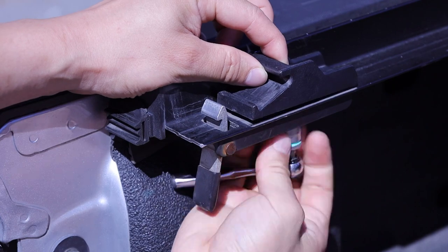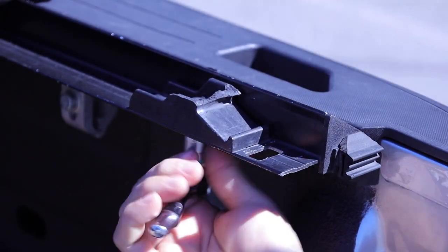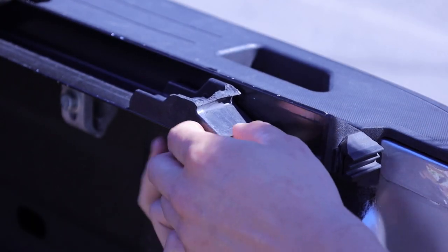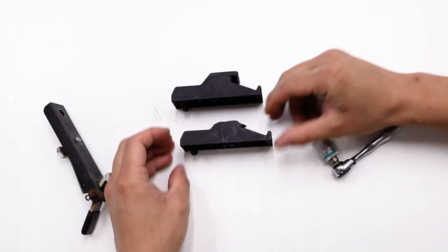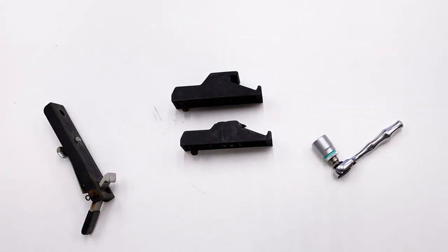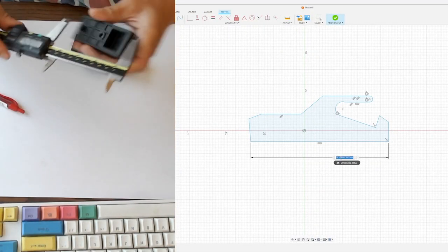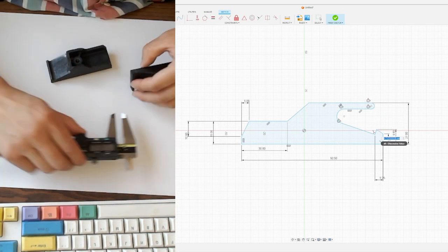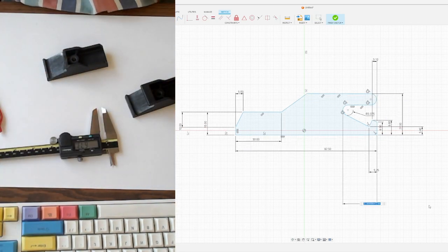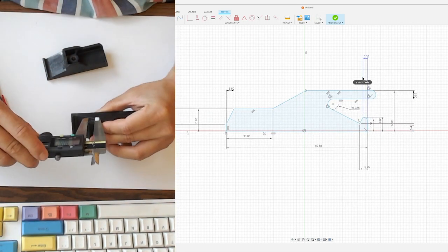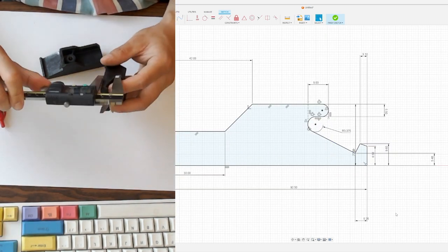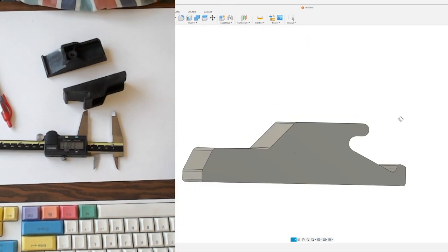Now, these parts are injection molded out of, I think, a fiber reinforced polymer. And one of the limitations with injection molding is you can't have very thick features. And in this case, it means that the back of the lip that holds the cover down isn't very well supported. So by 3D printing these out of nylon 12, we can make these way better supported and hopefully a few times stronger than the OEM component.